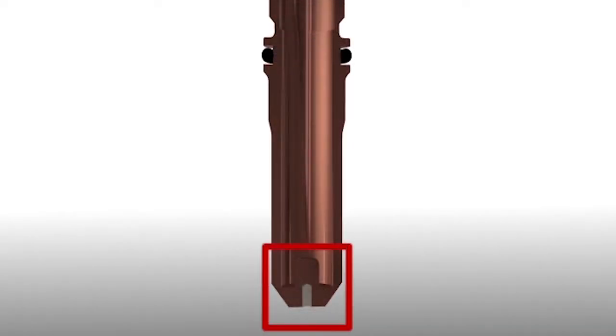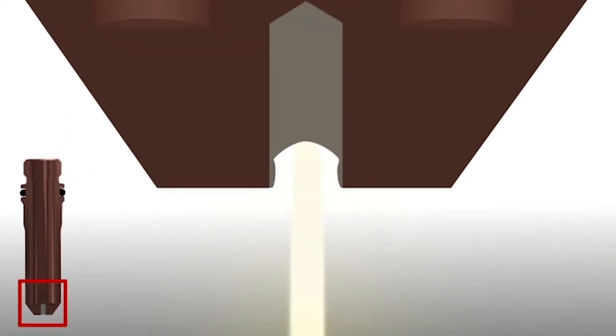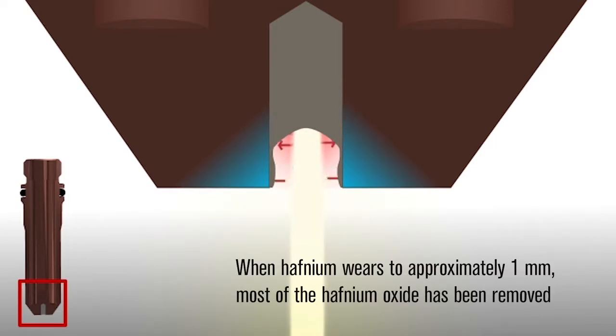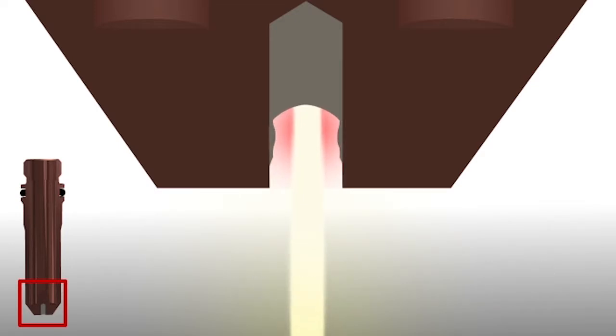When plasma cutting with a copper electrode, a layer of hafnium oxide forms on the walls of the electrode as the hafnium wears. It acts as a heat shield protecting the copper from the plasma arc. When the hafnium wears to approximately 1 millimeter, most of the hafnium oxide has been removed from the electrode walls, exposing the copper to the heat of the plasma arc. The heat generated by the arc melts the copper, and if enough copper melts, catastrophic failure of the electrode and nozzle can result.